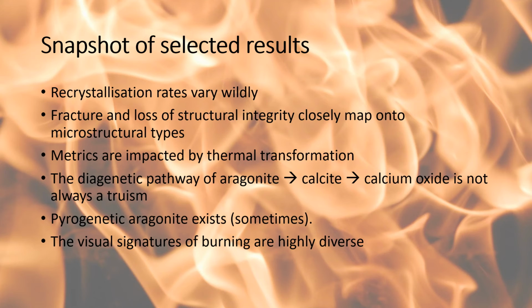And her results, combined with other experiments which we ran in the lab, yielded, I guess, the following statements which could be made. Recrystallization rates across different types of shell under different conditions vary wildly, absolutely wildly. There's some shells, very robust, where you'll get a near total recrystallization after only 5 minutes, just sitting on hot coals, not even exposed to flames, while others, like the example I've just given you, retained most of their aragonitic structure after 10 minutes in direct flames at temperatures over 600 degrees Celsius.